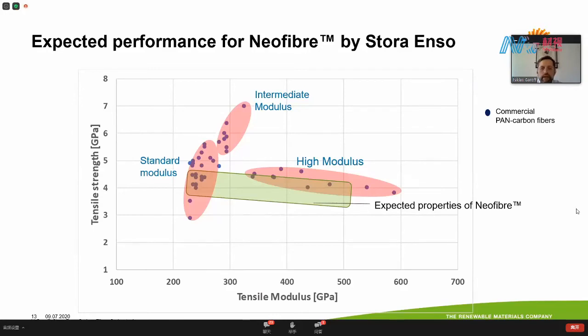So we have actually already produced carbon fibers with moduli up to 500 gigapascal. And what we are now doing is upscaling this process using more sophisticated equipment, and thereby we will reduce the defects in the fiber and increase the tensile strength. So we are quite confident that we will be able to produce good standard modulus carbon fiber.